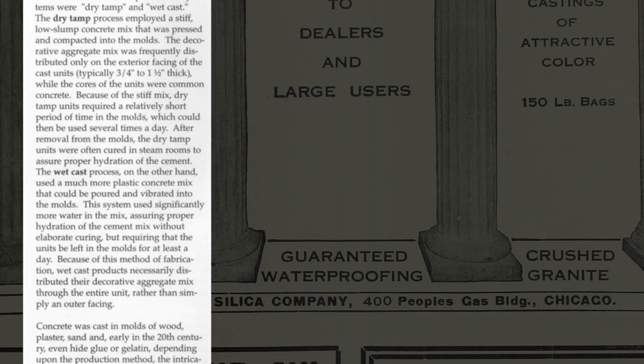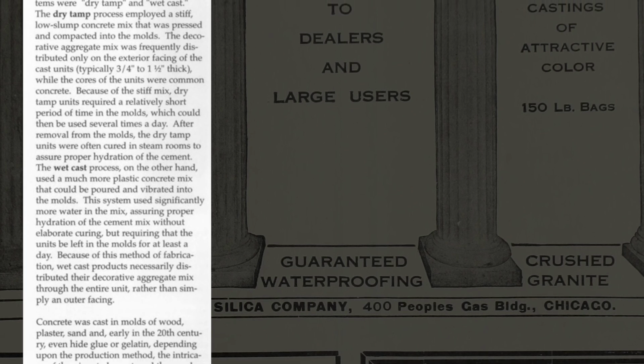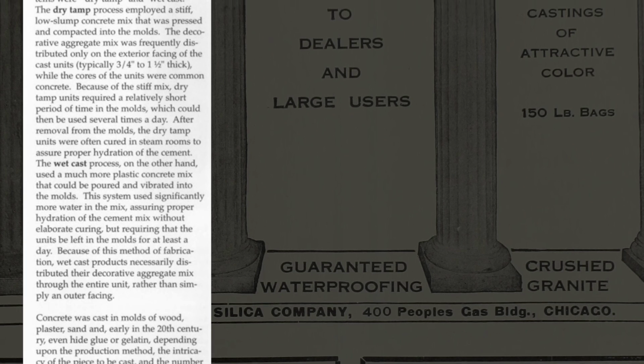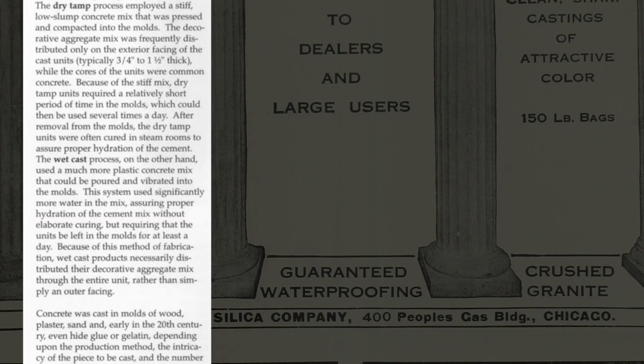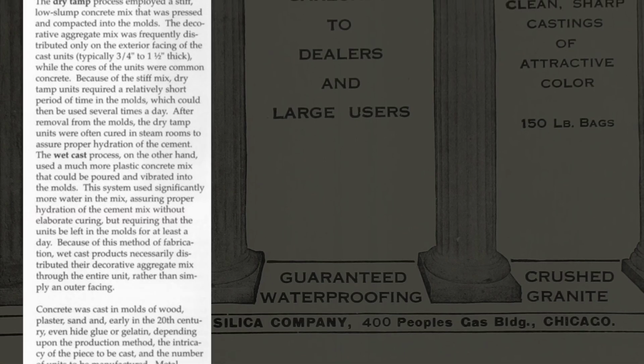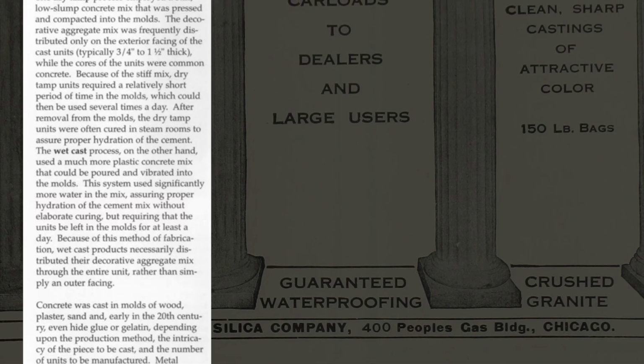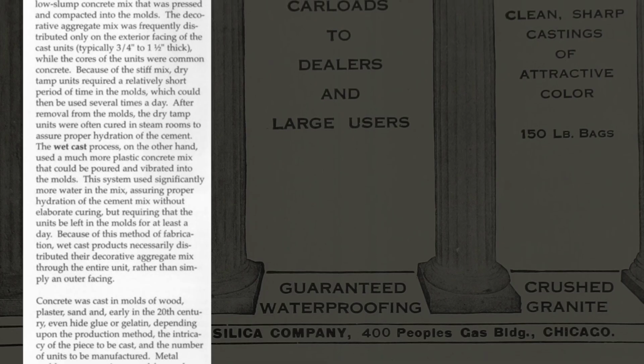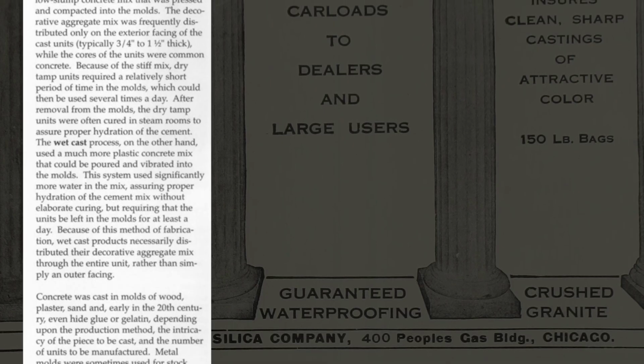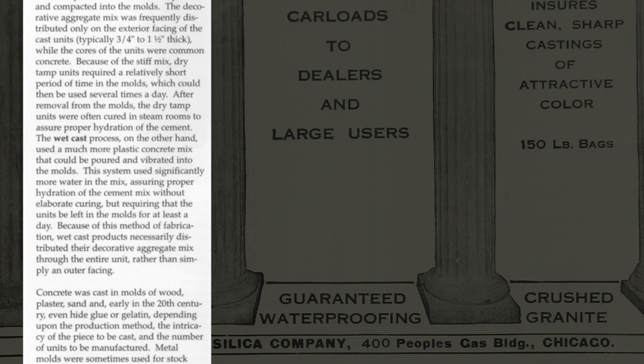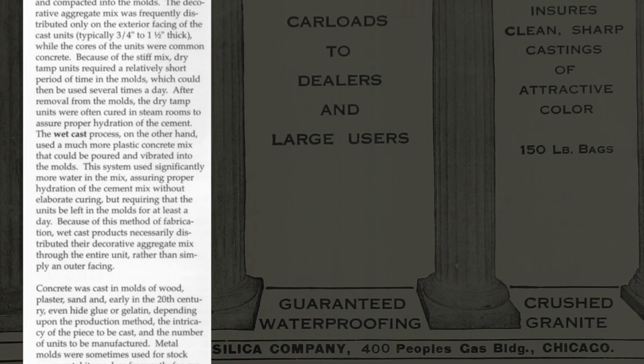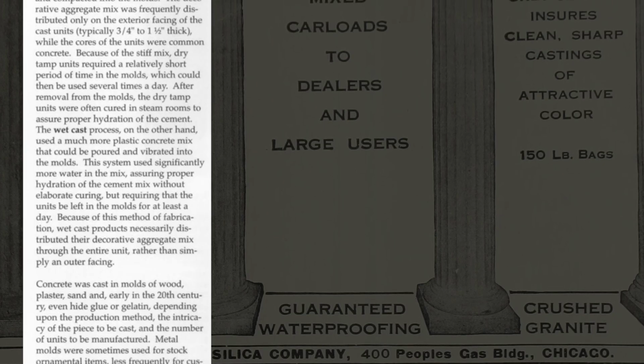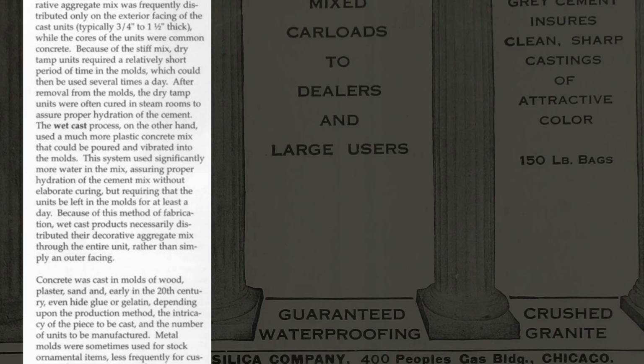This system used significantly more water in the mix, assuring proper hydration of the cement mix without elaborate curing, but requiring that units be left in the molds for at least a day. Because of this method of fabrication, wet cast products necessarily distributed the decorative aggregate mix through the entire unit, rather than simply on the outer facing.